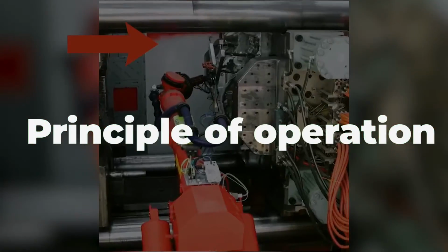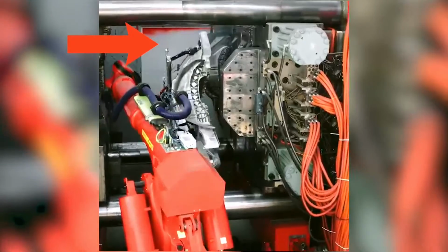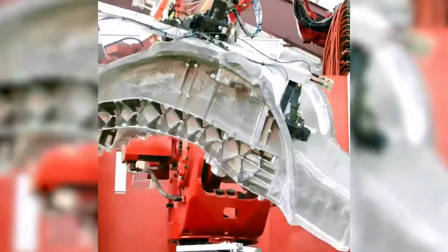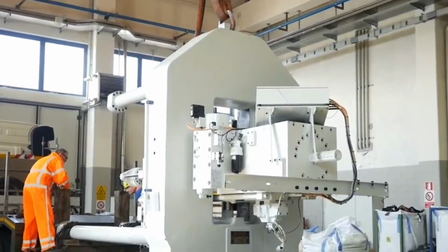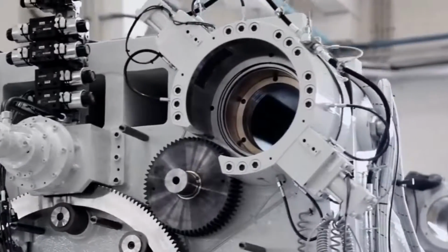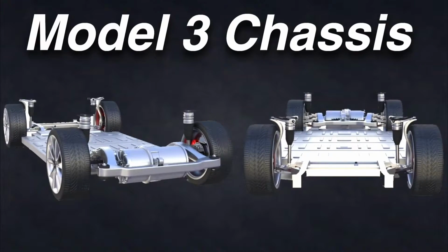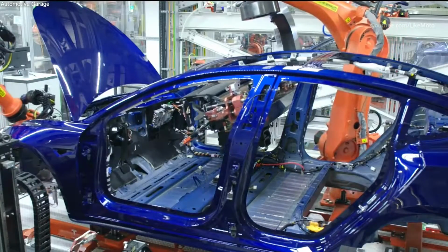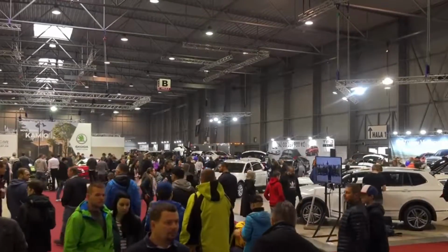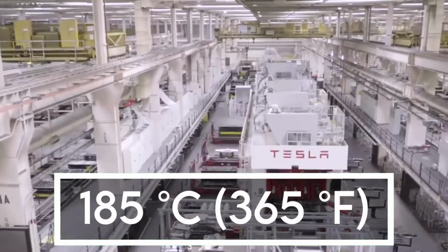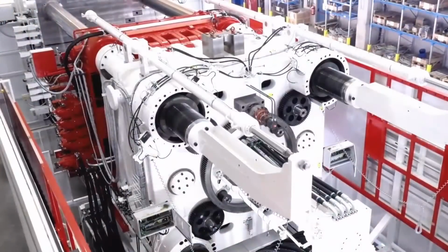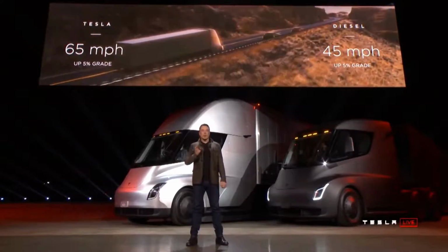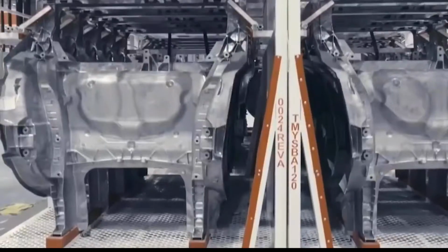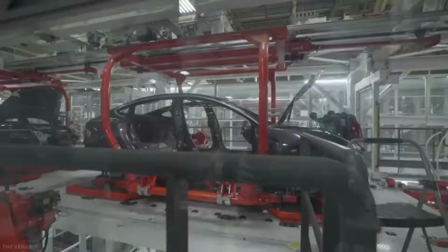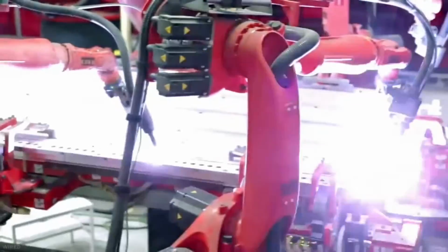Principle of operation: GigaPress in closed position during casting, plus after removal of previous casting, and in open position for robot removal of casting plus cleaning. Die casting works by forcing molten metal alloy inside a reusable mold, then opening the mold to remove the finished piece after it has solidified. The open mold is cooled to 185 degrees Celsius, 365 degrees Fahrenheit, and cleaned by robots, and fresh molten aluminum is prepared for the next cycle to begin 1 to 2 minutes after the first cycle. Each fresh casting is trimmed to approximate size, measured, checked for imperfections, and sent for CNC machining to finished size.